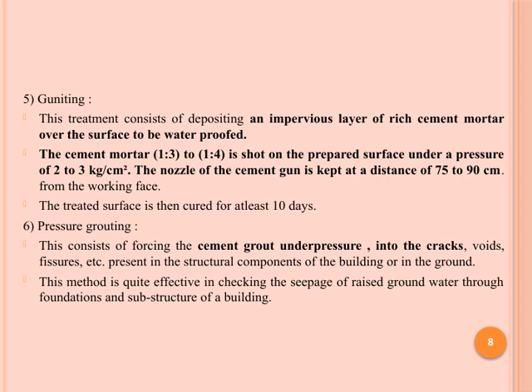When doing this, it's important to keep the nozzle of the cement gun at a distance of roughly 75 to 90 centimeters from the surface to ensure even application. After applying the gunniting, the surface must be cured for at least 10 days to achieve the desired strength and waterproofing effectiveness. Now, moving on to pressure grouting, which complements gunniting quite well.